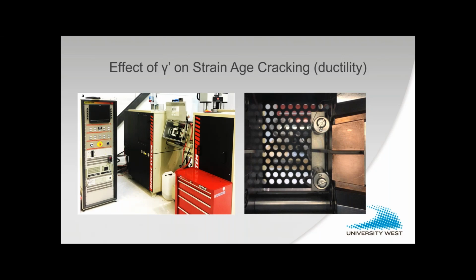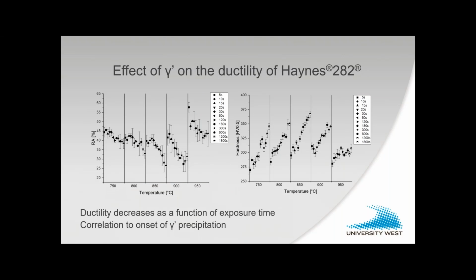to get more insight to what's going on in the material. So here are some of the results that we did on Haynes 282, which is a reasonably newly developed superalloy. So to the left-hand side, you can see the reduction in area versus test temperature with varying exposure time. So we can see by increasing the exposure time, ductility drops. And the ductility drop is most significant for temperature 850 and 900 degrees C. And we can also couple that to the strength of the material, in this case, hardness. We see increase in hardness by increasing exposure time at these different temperatures.